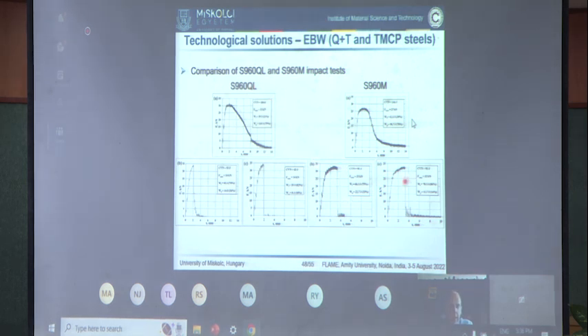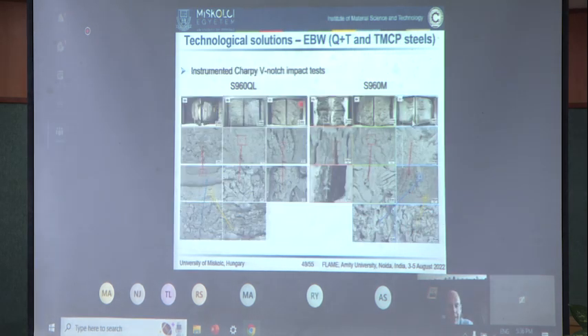However, some brittle parts are also identified in the weld or in the heat-affected zone, but in total, the absorbed energy is generally higher, and the TMCP high-strength steel welded joints are more ductile compared to the quenched and tempered grade of the same category. Here you can see also the fractography analysis and the geometry of the Charpy specimen, the fracture surface. Generally, a larger amount of plastic deformation is identified in TMCP steel of the same strength category.